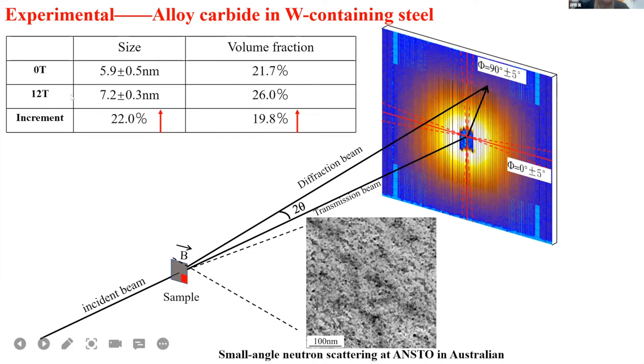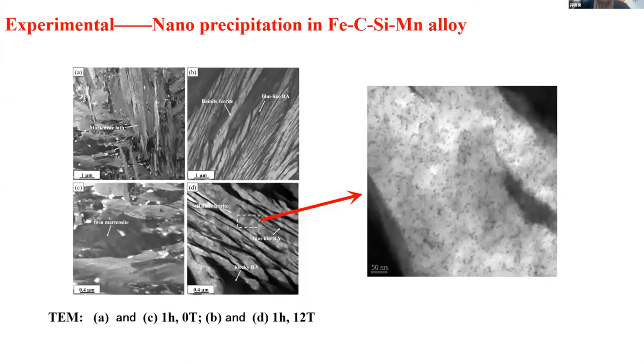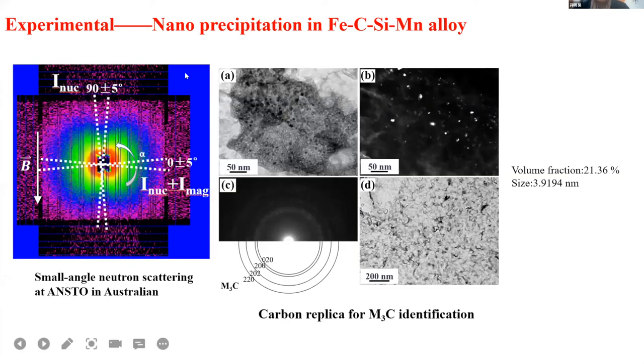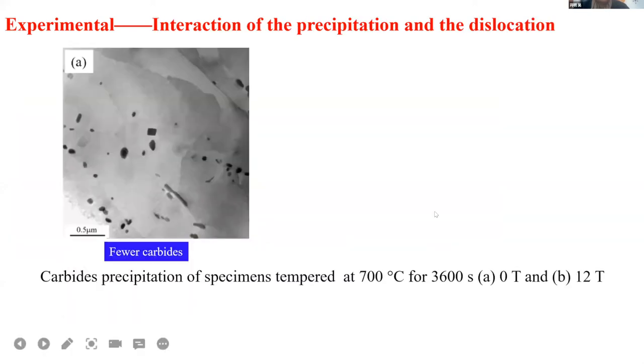From this result, under the magnetic field, the size increases and the volume increases as well. So, not only the alloy carbide, but also the cementite. It is supposed to be that if the silicon is high, the silicon will retard the precipitation of the cementite. But in our experiment, under the magnetic field, the cementite comes out. So this is the characterization of the cementite, using carbon replicas.